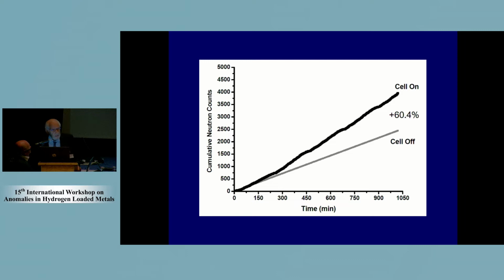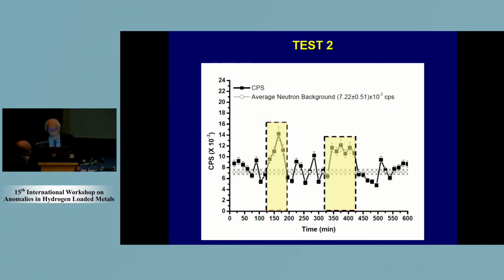Then for the same time period, 20 hours, we have this cumulative graph for cell off and cell on. It means background and, of course, CPS during the test. And you see that there is a fork of about 60%, which is a very considerable result, I think. Then test 2 is only 10 hours. As you see in the horizontal axis, we have 600 minutes, and we had smaller peaks, only 2 peaks, even because there is a shorter time, and the first peak is around twice the background.